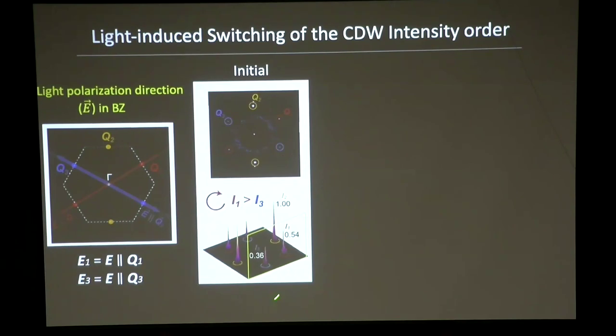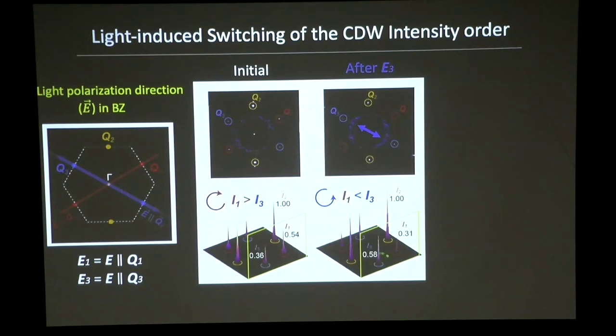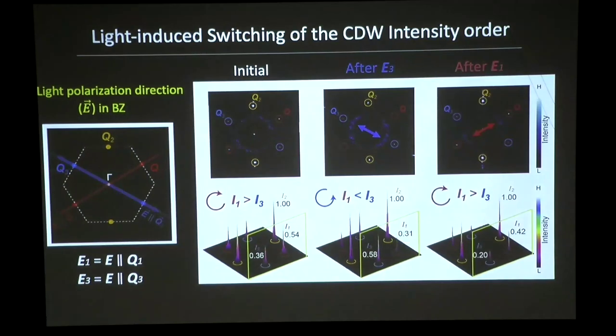So let's start here. And so you can see these are the six charge density wave peaks. I1, this is this peak, is higher than I3. Okay, great. Now I'm going to shine light along this direction, the I3 direction. And now you can see I3 is greater than I1. And now I'm going to shine light along I1 again, and you can see I1 is greater than I3. So what we're doing here is that by shining light along different directions, we're manipulating the intensity of the charge density wave. Okay? Okay, so far so good.